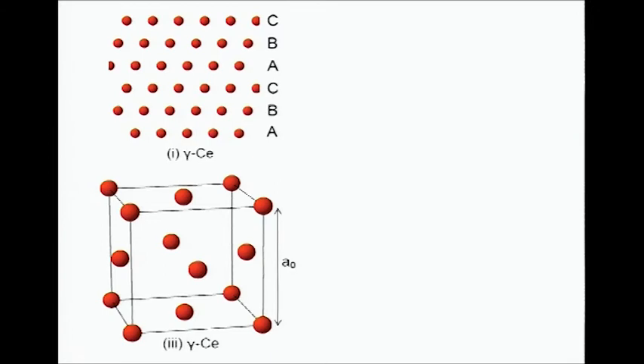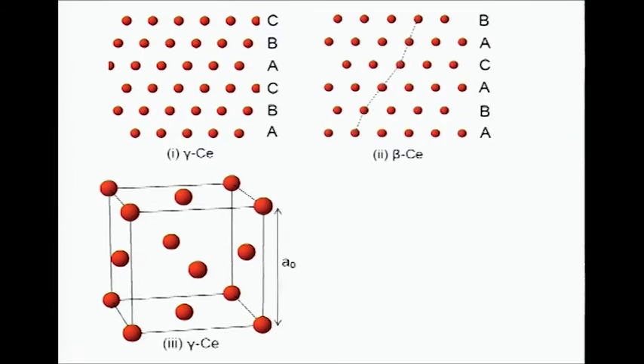But when you get this beta phase, it's actually the same thing as the FCC structure with a stacking fault. So the stacking sequence goes A, B, A, C, A, B. So you get this stacking fault. It acts as a sink for dislocations. And so it's very close to the FCC structure.